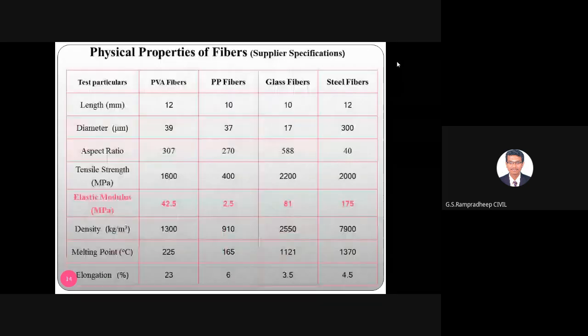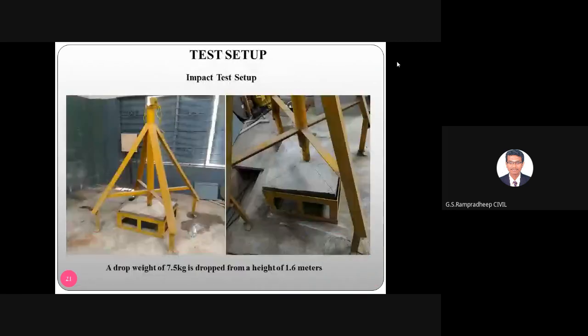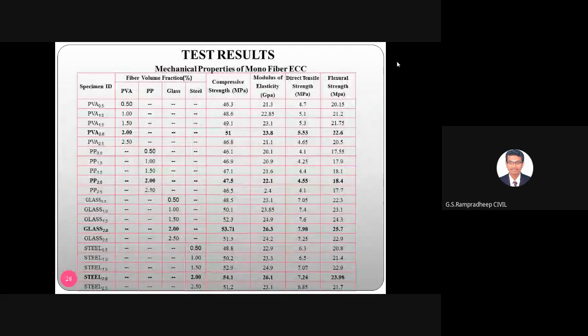Where we have seen here, yes. You just see the tensile strength is 2200 for glass and 2000 for steel fiber, and because of this, there is a slight increase in the flexural strength for glass compared to steel. And you can also compare the tensile strength, 7.98 and 7.24, just a 0.5, 0.6 difference. But why is it so? Because glass fiber has a tensile strength of 2200 MPa, whereas steel is 2000 MPa, right?